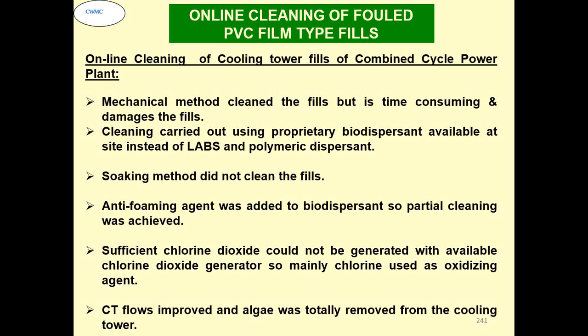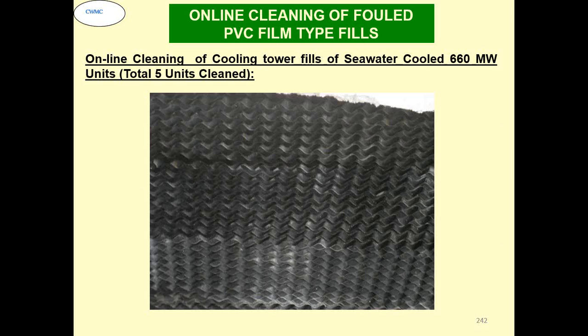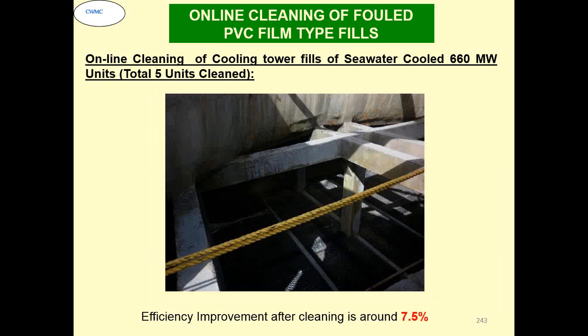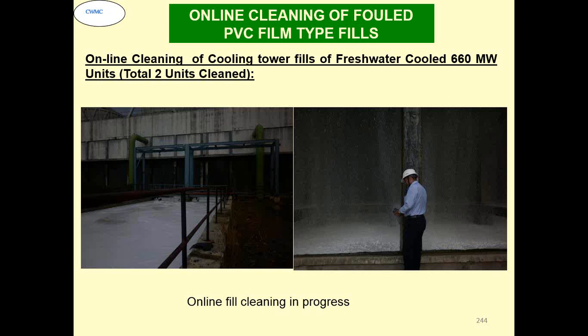Then the online cleaning that we developed is based on linear alkyl benzene sulphonate and a polymeric dispersant. Using this method, we have done the cleaning. This is a seawater based system, 660 megawatt, 5 units totally cleaned. You can see the cleaned fills. There was an efficiency improvement of about 7.5%. Then for freshwater fills, we have done 2 units. Again, the second time the cleaning has been done.